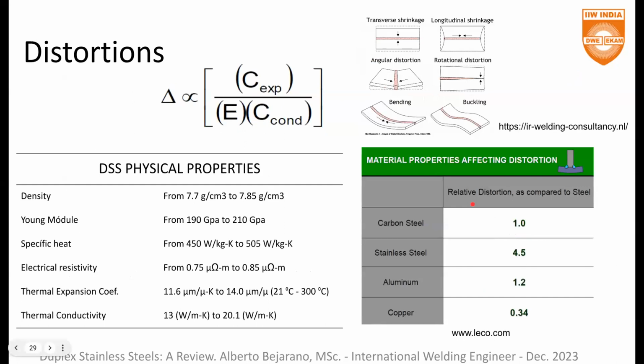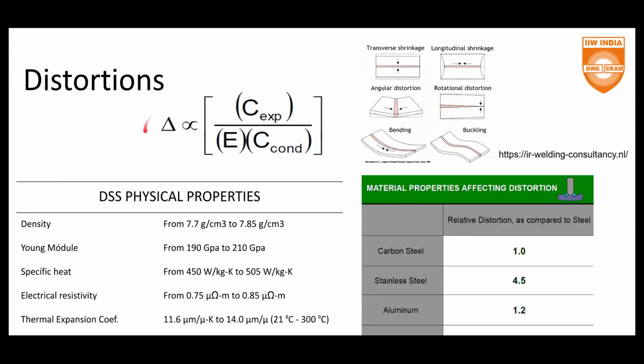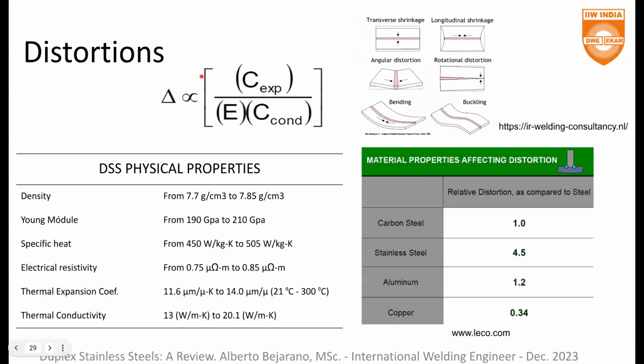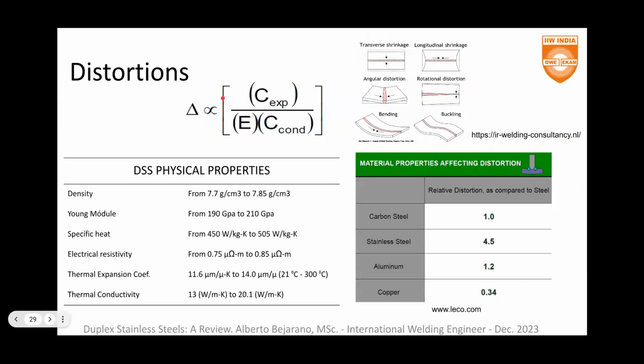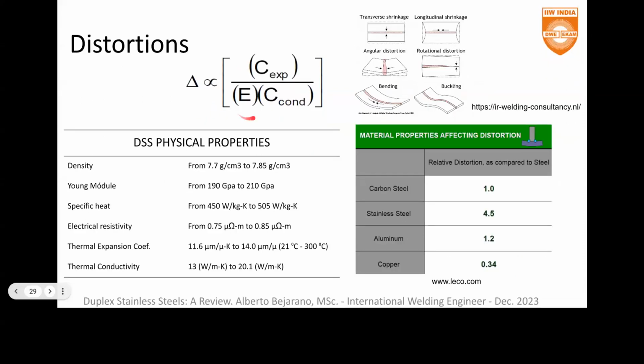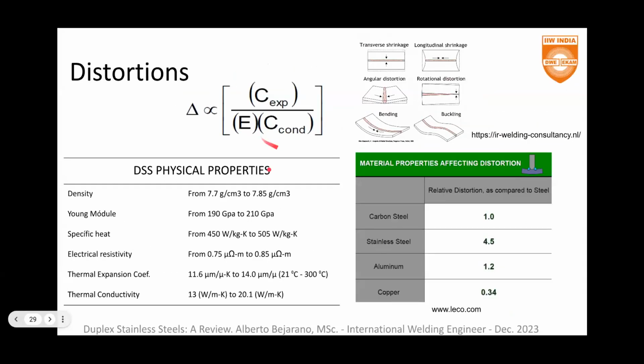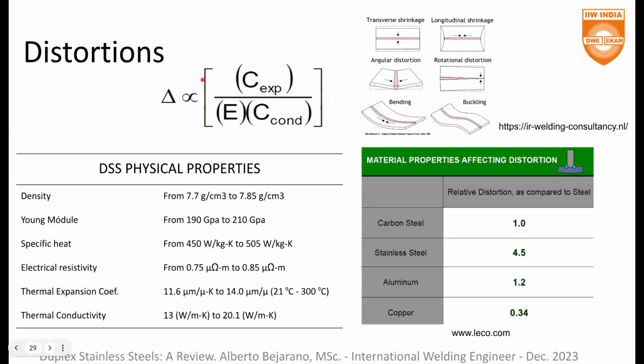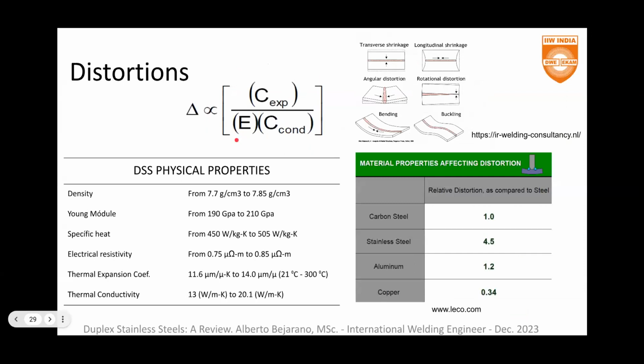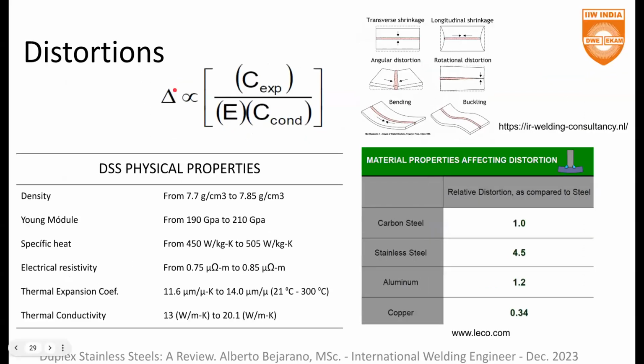And the reason for that is the relationship that exists in the physical properties of our base material. The base equation that we have in mind is this one. The distortion is proportional to this relationship. So if we have a higher Young modulus and a higher conductivity, we have lower distortions. And if we have a higher thermal expansion coefficient, of course, we will find at the end of the day more distortions.